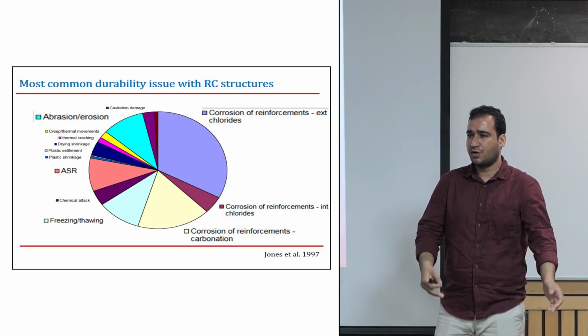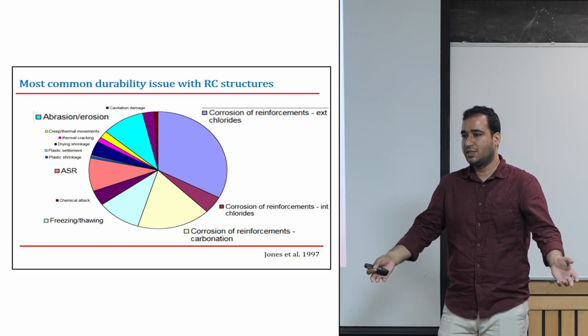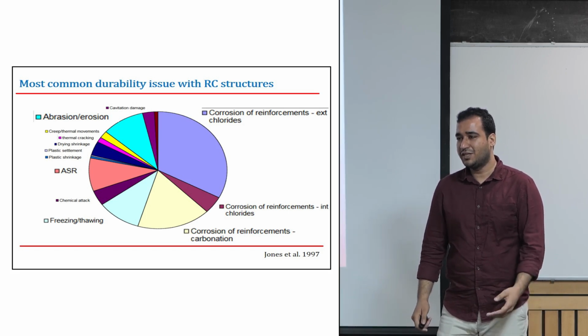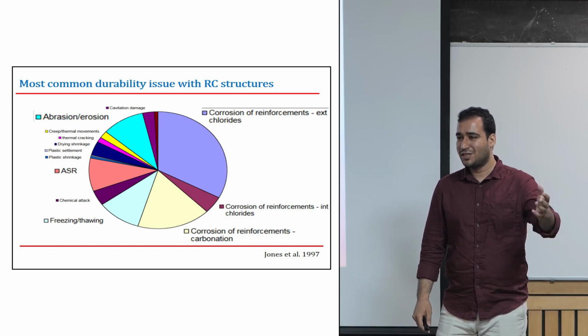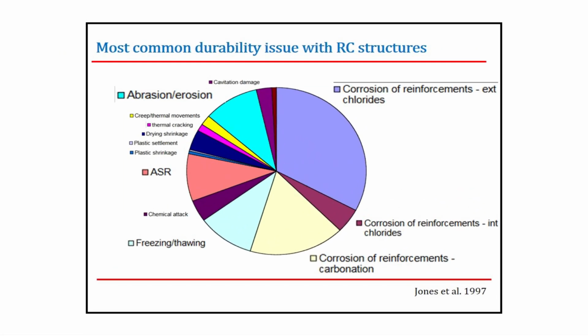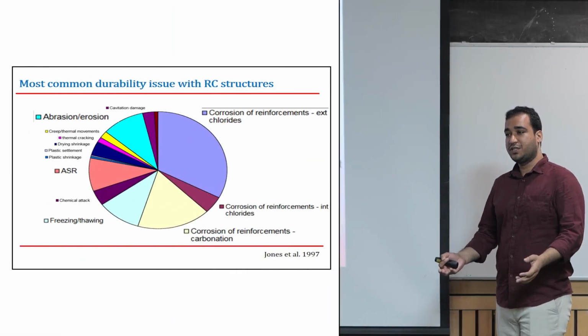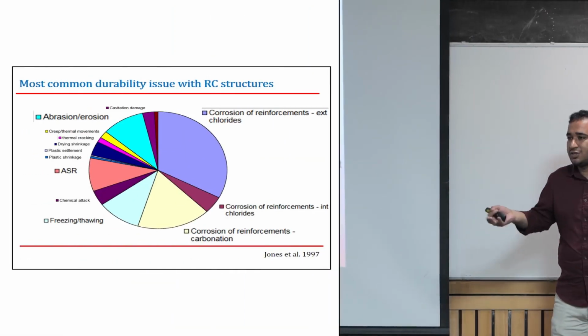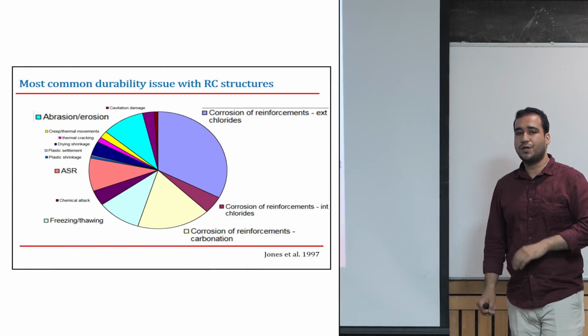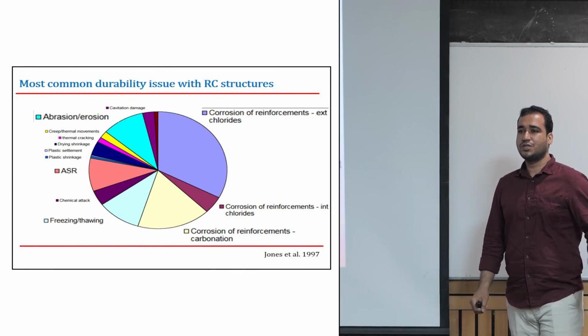10% of issues will be corrosion, 20% or more than that? More than 10%. More than 10, 20, more than 30? Surprisingly, you are well aware, but it's even more than 50%. So you see, most of our issues are corrosion only. The cause of this corrosion can be different, be it admixed chlorides, chlorides coming from the outside, or carbonation, or a macro cell of some kind. But the cause is different, and more than 50% is corrosion.